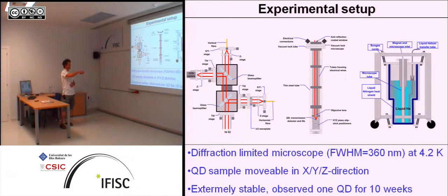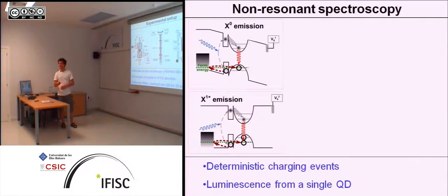And on top of that sits a detector, the quantum dot sample, and the cell, but I will show another picture of that later. And then all of this basically goes inside of this liquid helium cryostat. And this modular design is basically used to optimize all single components while still providing high stability. So we managed to observe a single quantum dot, which is all the way down here, and for 20 nanometer sized object for 10 weeks, I think was the longest time now, with refilling helium and everything else.